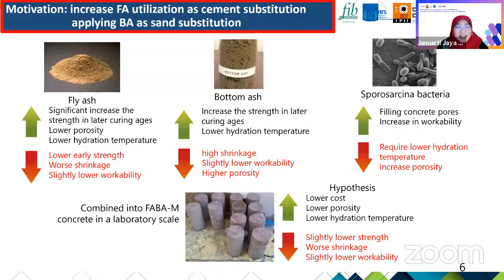It is not as much as Sagawa Sensei's explanation before, but we have done our best. It has a positive and negative effect to the concrete. It increases the strength at the later age. It has also lowered the porosity and decreased the hydration temperature. However, as a pozzolan, it has a lower strength at the early age and contributes to high shrinkage and makes the workability lower if we use more than 30% by cement weight.